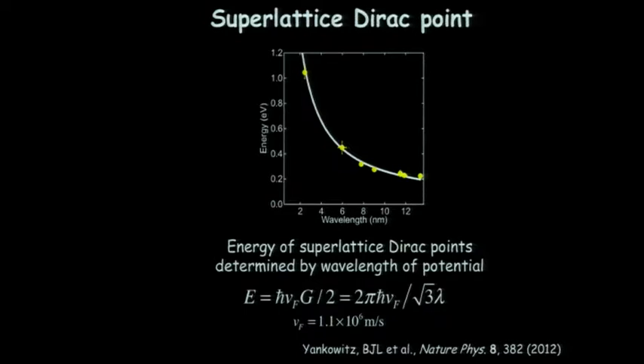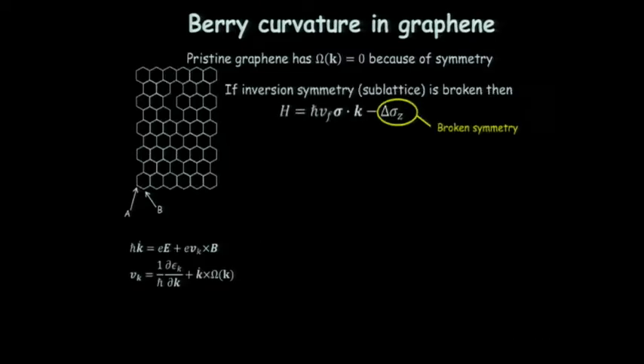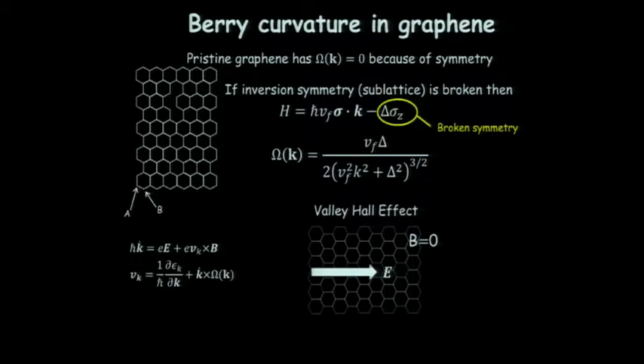And so we're interested in seeing, what other properties can we modify at lower energy in the graphene with the boron nitride. And so ideally what we would like to do is break the inversion symmetry of the graphene and actually open up a band gap in it. So here we have our normal Hamiltonian, which gives the Dirac spectrum here. But if we can break the symmetry, we could open up a band gap in the graphene. And so this Berry curvature would be non-zero, and we could do interesting things like the Valley Hall effect.